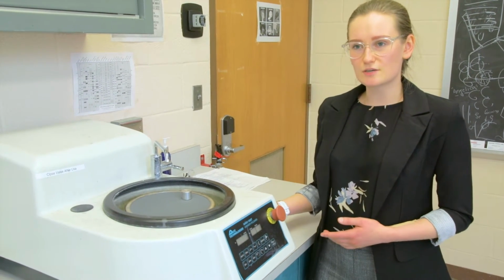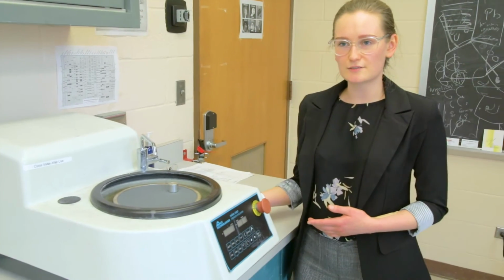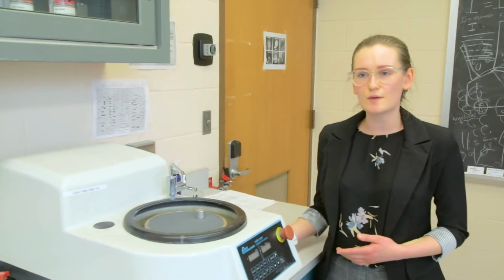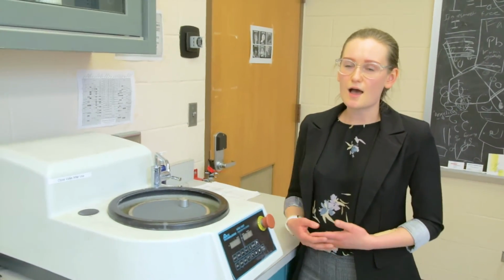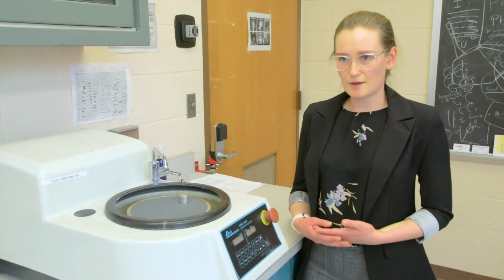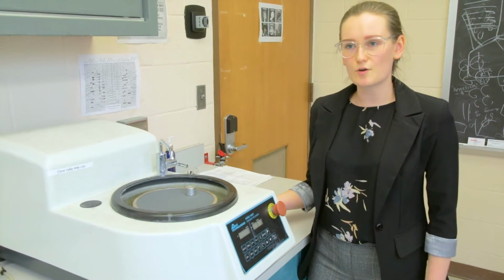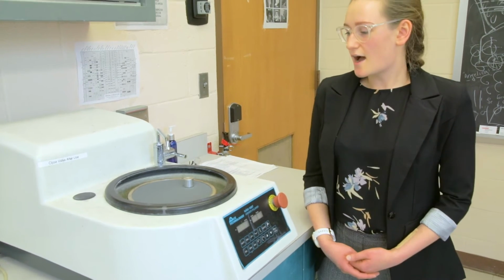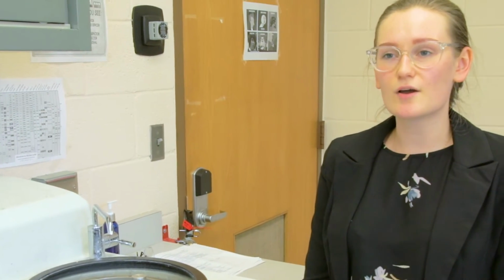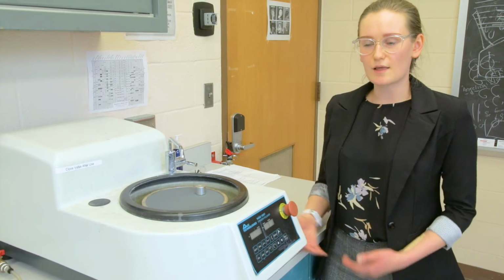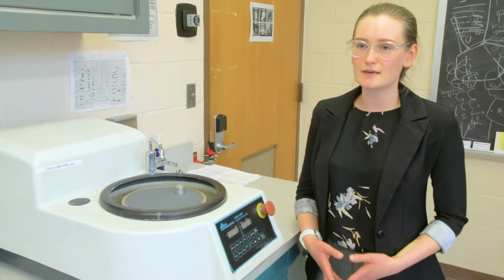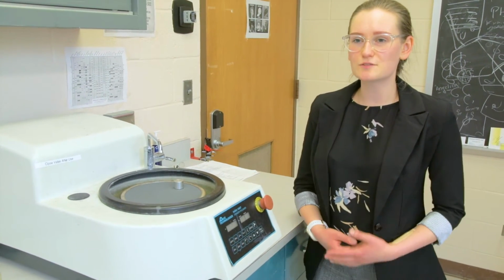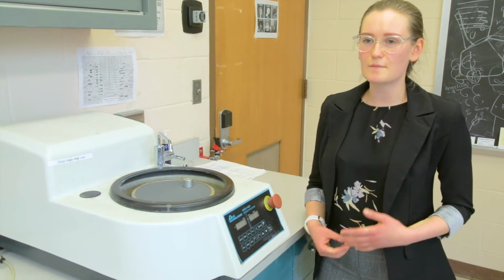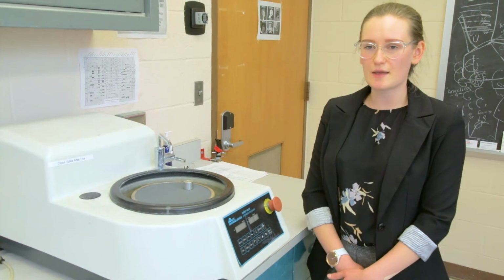So we have been looking at a particular class of high entropy alloys in the refractory section containing elements such as zirconium, niobium, tantalum, vanadium, and molybdenum, along with another system containing iron, chromium, nickel, and manganese. These samples have been prepared for us by the Idaho National Lab, which we are working in collaboration with, along with Bowling Green State University in Ohio, which is also working on observing positron annihilation spectroscopy in these same alloy samples.